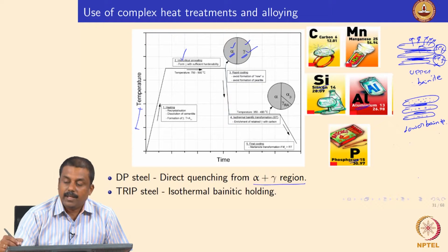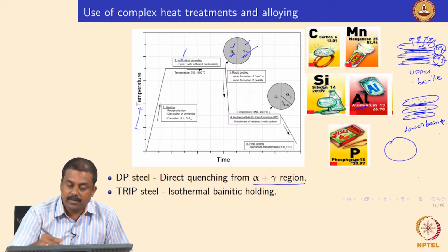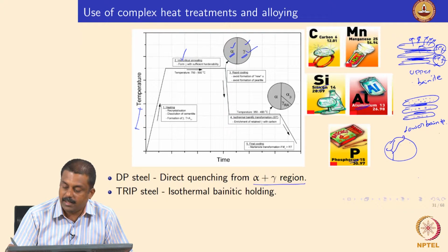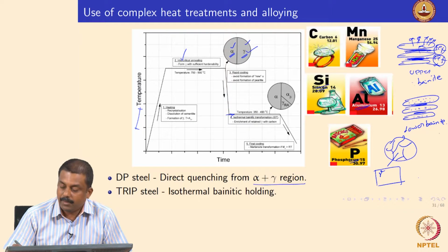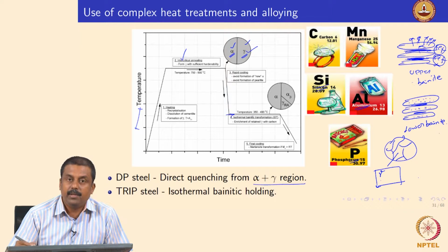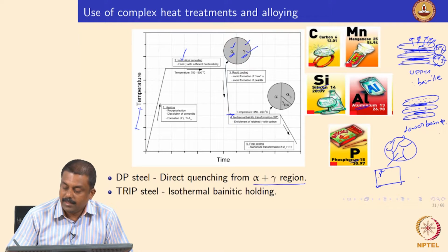Suppose you imagine the austenitic, two-phase microstructure from the intercritical region. For example, this is an austenite grain. If you make it bigger, imagine this is your austenite grain, and it is now held at the temperature where you form bainite. Okay. So, what will happen at this temperature? You tend to form a bainite microstructure. The austenite transforms to bainite during this holding. You first nucleate a ferrite lath, but this ferrite lath cannot hold carbon, right. Carbon has to be pushed out of the ferrite to the adjoining austenite regions.